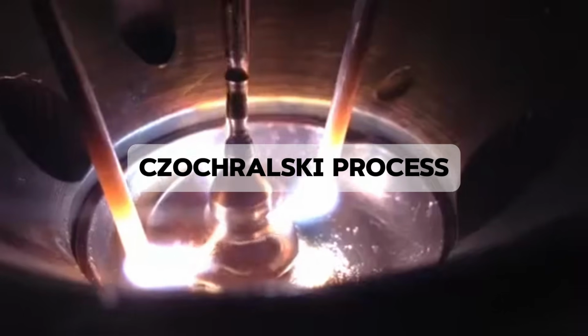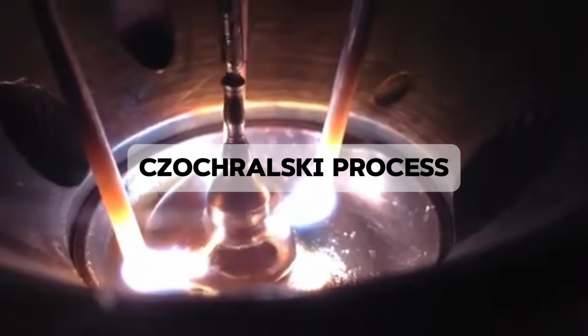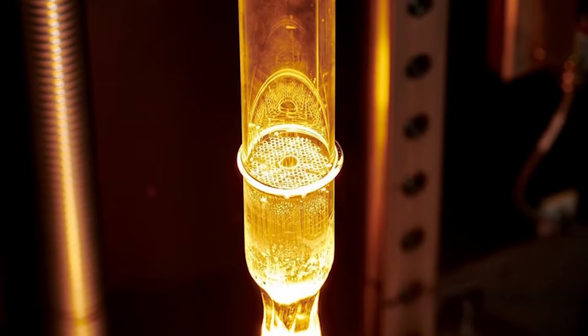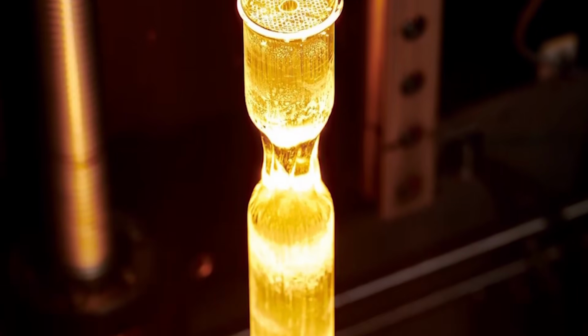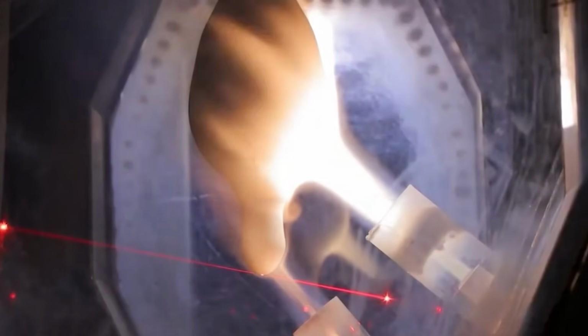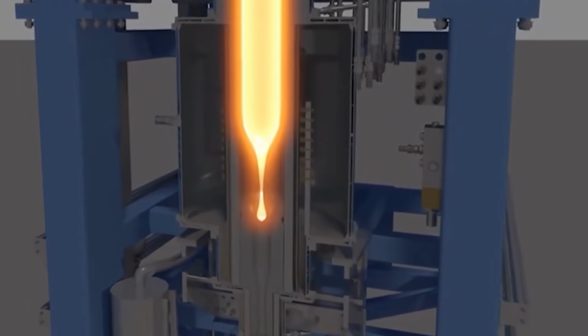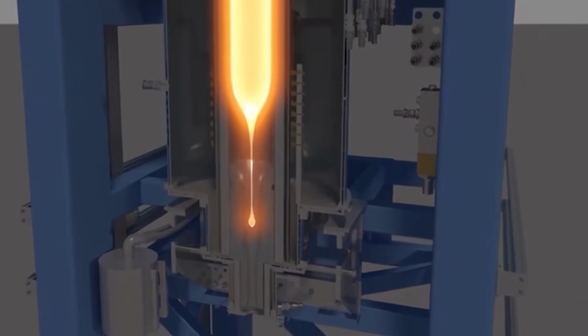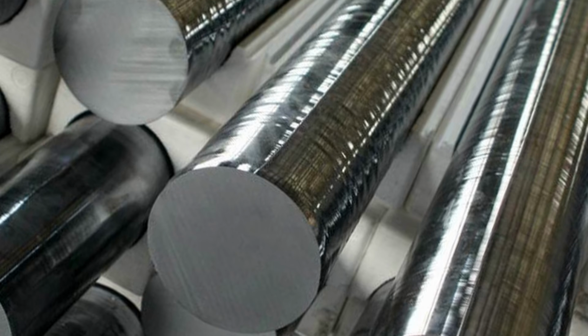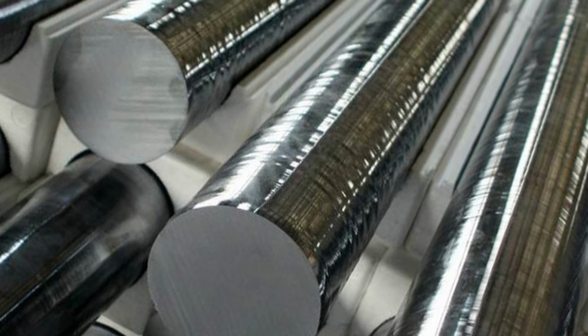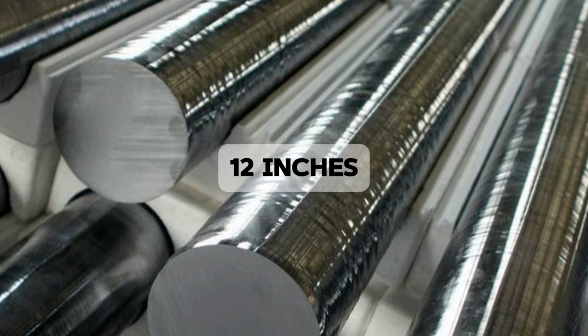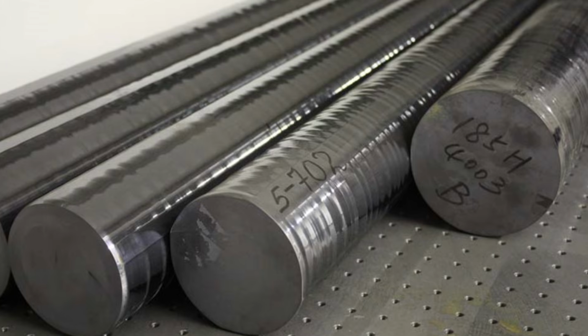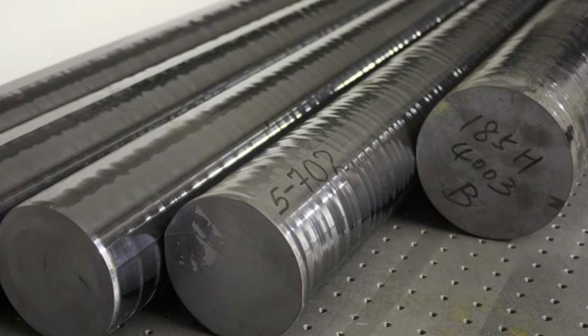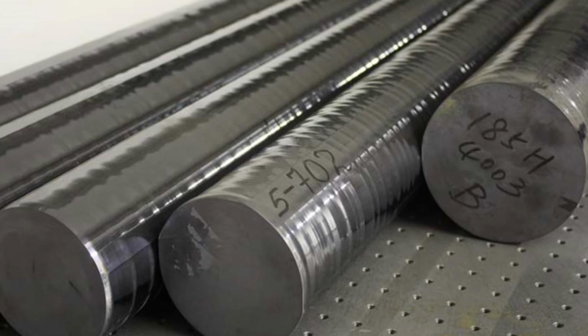This is the Czochralski process, and it demands almost superhuman stability. The pull rate is measured in fractions of an inch per hour. Temperature gradients are controlled to within a degree. Even subtle vibrations in the building can disturb the crystal lattice. Over the course of several days, the ingot grows into a gleaming cylinder up to 12 inches in diameter and more than 6 feet long, weighing hundreds of pounds. One continuous, unbroken crystal. Billions of trillions of atoms, all locked into a single perfect arrangement.